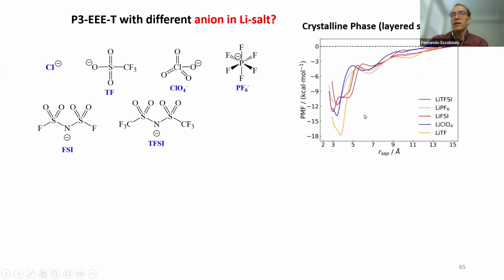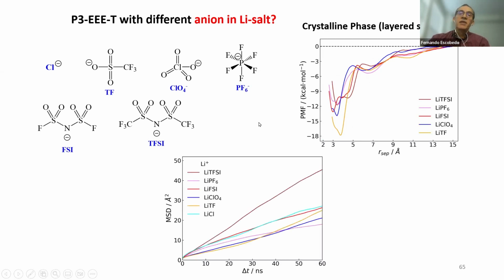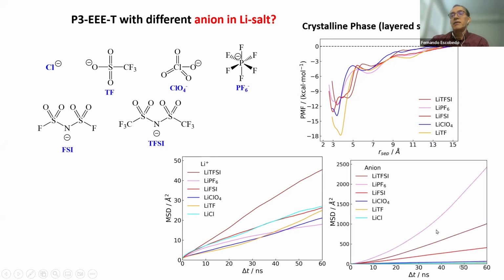And so it's amplifying here that there are some slightly better than others, but on the whole they're somewhat similar. Now, if you look at the mean square displacement, you can look at how the lithium moves in the simulations in the crystalline phase, these later structures, and see how things move in the PO region. You see that the lithium moves much faster when you have this TFSI ion compared to the other ones. The anion itself, there's some differences.